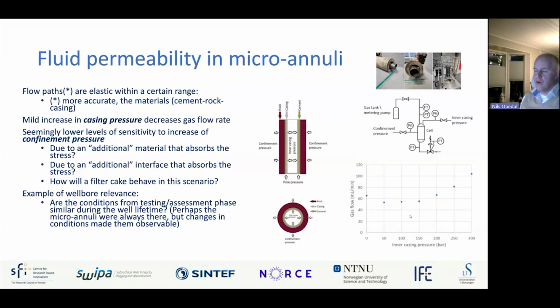An example of why we are investing in this is, in general, to see how different materials are behaving in terms of cyclic changes to stresses, also how the fluid permeability is behaving for different specimens. And for a more applied question, an example could be that an important feature here is whether the conditions in your well from the testing or assessment phase will be similar during the well lifetime. Because maybe you're assessing your well with a pressure test or leak tests. If the conditions are different later on, it could easily be that you will have a different kind of permeability than what you have in the initial phase. So it's important to know as much as possible about your well, about the material, mechanical properties, and also of any kinds of defects and or interfaces you might have in your well.